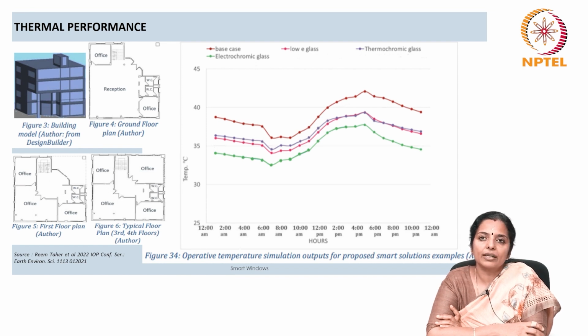Different types of smart glass retrofitting exhibit varying impacts, with electrochromic glazing standing out for achieving the most significant thermal improvement, reducing operative temperatures by approximately 3 to 7 degrees centigrade. In contrast, thermochromic glazing shows the lowest thermal performance with a reduction of about 2 to 5 degrees centigrade.